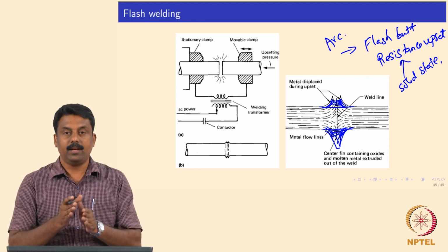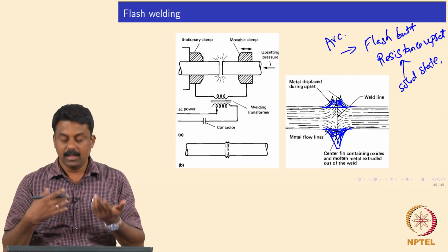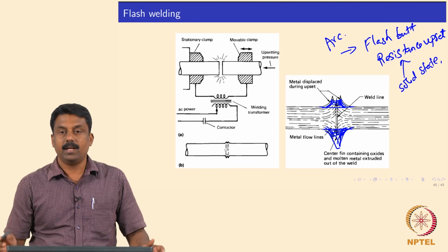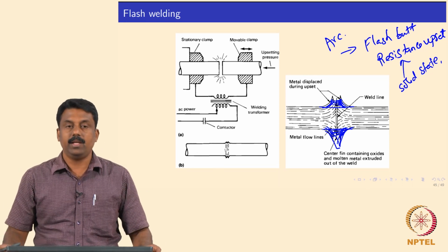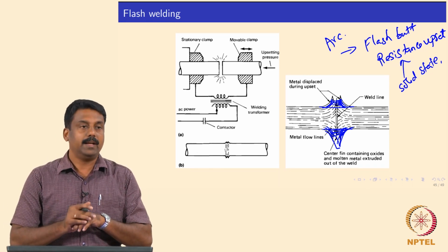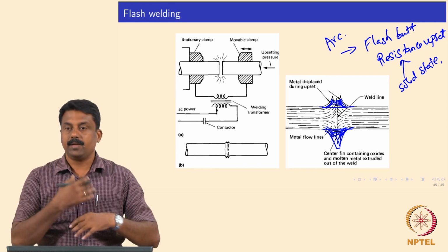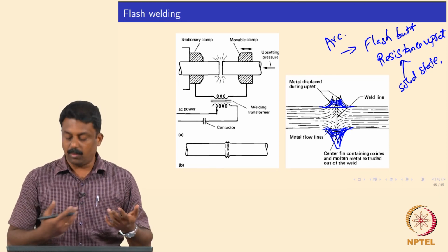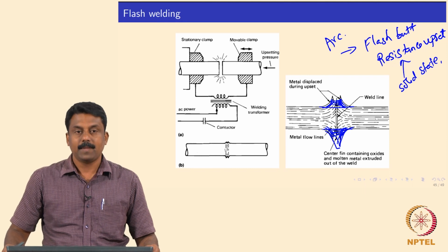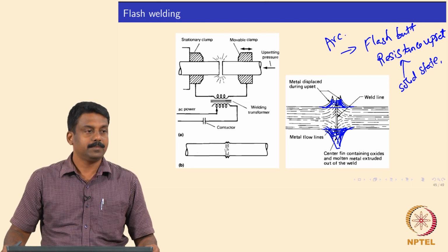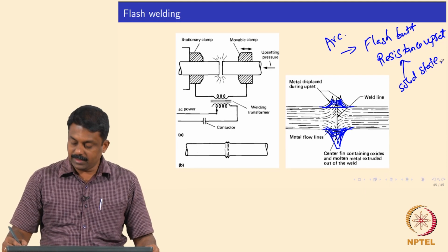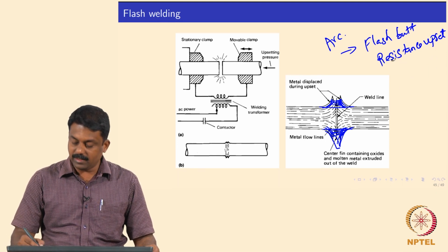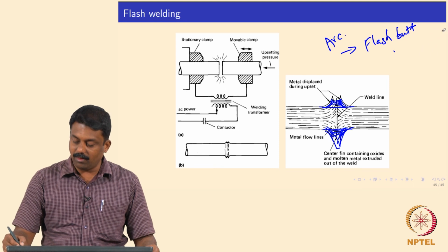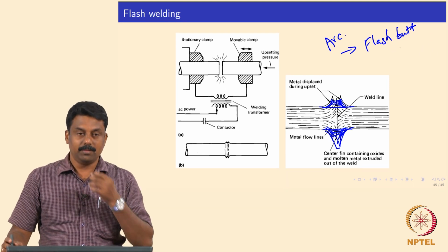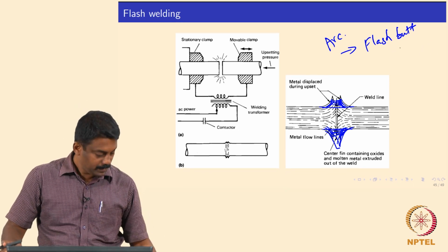So we will have a heating of the interface leading to decreasing yield stress, and then subsequently with a reasonably compressive load you can mechanically deform the interfaces and coalesce to form the weld. It is clear, the difference is very important. So if someone says that both are the same, or says the welding process you are using is resistance upset welding where the arc is there, then it is wrong. Okay. So this classification is different.